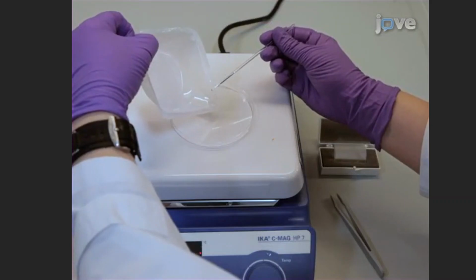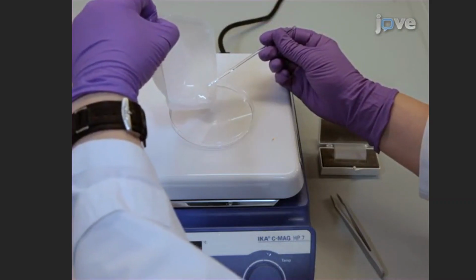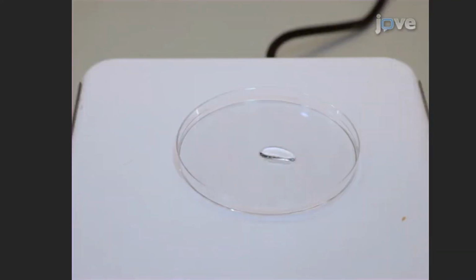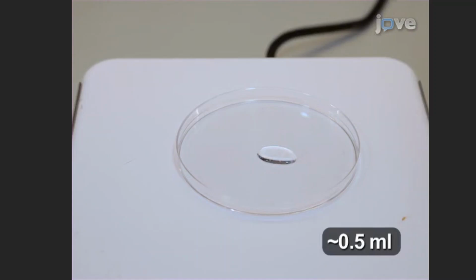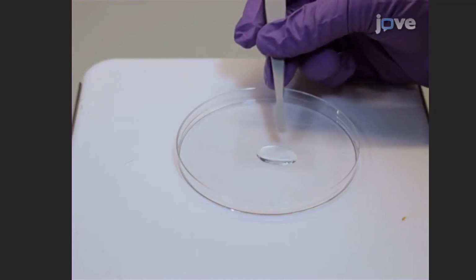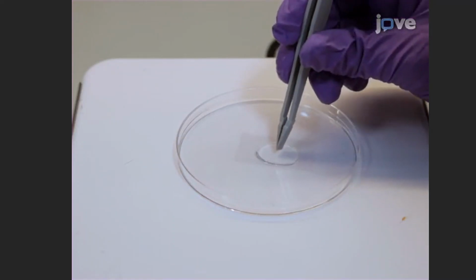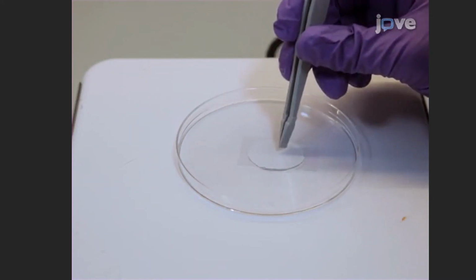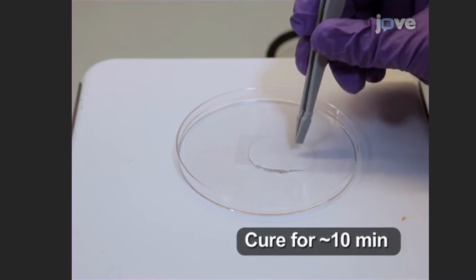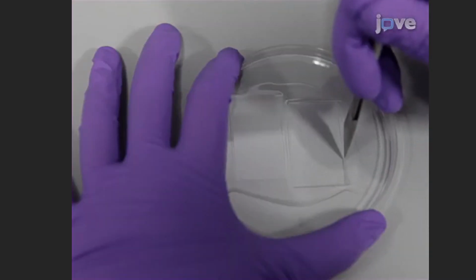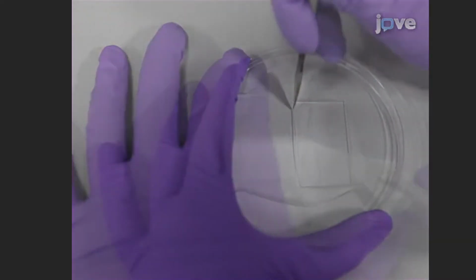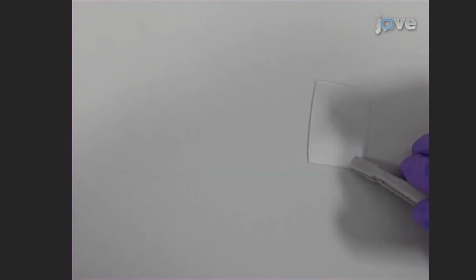Next, prepare a thin PDMS layer mounted on a glass cover slip by pouring a small amount of the PDMS curing agent mixture onto the petri dish. Press a cover slip onto the PDMS layer, place it on the hot plate, and thermally cure it for about 10 minutes.